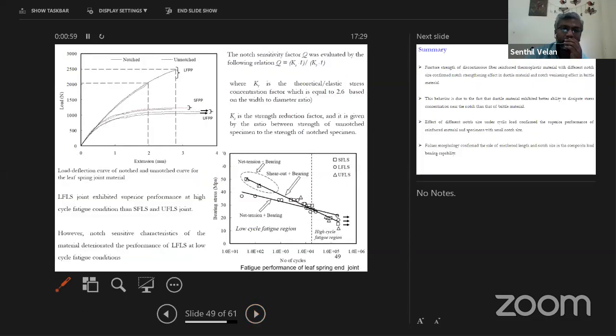So this was the slide we were trying to finally achieve. If you look at the notch sensitivity, we have considered three classes of material, and we were trying to understand how the notch sensitivity varies. In this portion, you will see the final bending strength, between low cycle and high cycle. Any machine element subjected to fatigue needs a different design approach or strategy, because this behavior will be completely different under 10 power 4 and beyond.